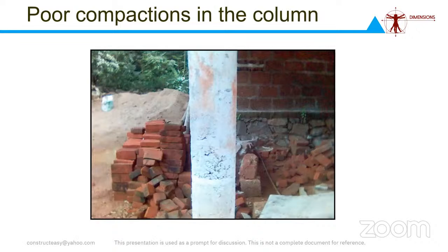If you look at the column here, there is some honeycombing. People will say, no, nothing to worry, sir. We are anyhow going to plaster it. But will your plaster enter all these voids that we are seeing here? No, plastering is only a superficial coating you have given, which means you are locking a pocket of air inside, which can expand when the temperature goes up, which can provide space for moisture to be present there whenever you have rain splashing or when you yourself cure, and then it will attract moisture inside. So this moisture stays inside, attacks your steel, and initiates the corrosion process. So all these kinds of defects should be avoided at the stage of making itself.